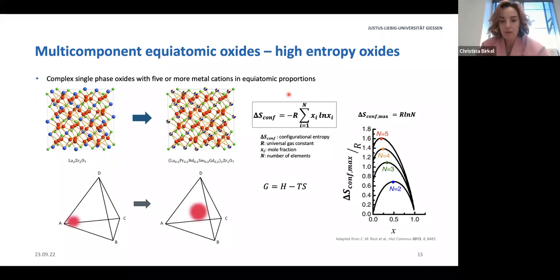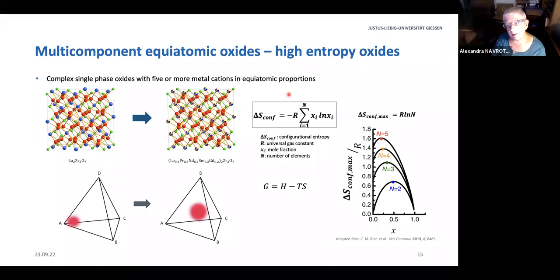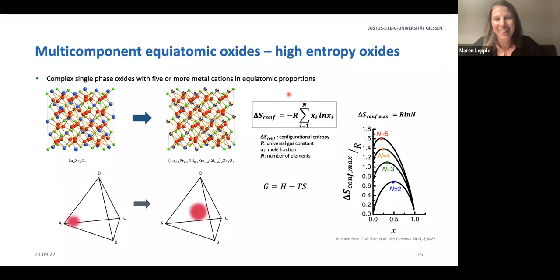Okay. Thank you. All of that tells you about long range order that you catch with X-ray, but certainly our experience with pyrochlores and perhaps with defect fluorites as well is that there are all sorts of funny short range order things going on, which would stabilize the energy and diminish the entropy. So I'm not sure that quote unquote high entropy oxides are any higher entropy than high entropy alloys. It's a matter of the scale of short range ordering. Yeah, I agree. I totally agree.